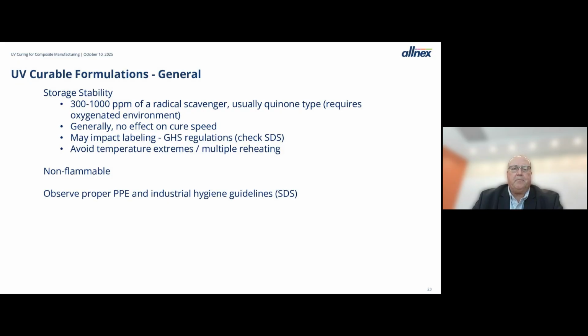And finally, if you have drums or totes or whatever, try not to reheat them multiple times. Every time you heat up a tote, you are consuming a little bit of that stabilizer. And if you do multiple reheats, you may reach a point where you've consumed all of the stabilizer. This isn't a couple reheats. This is multiple, 6, 7, 8 reheats. But just try to avoid multiple reheating of UV curable formulations because you are consuming the stabilizers when you do that. UV systems are generally non-flammable. And then just as always, read the SDS, wear proper protective gear, and follow industrial hygiene.